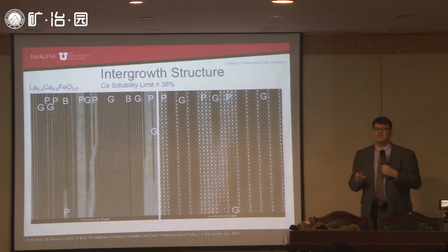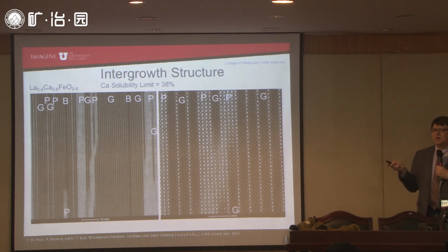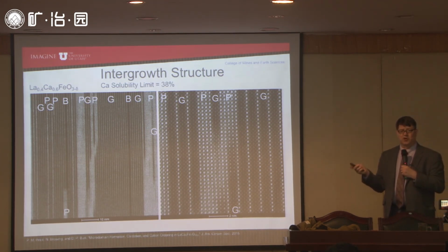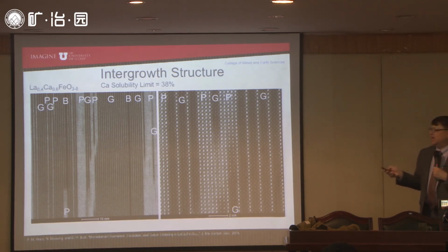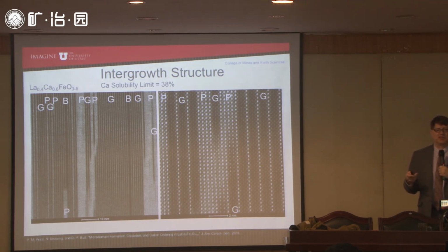And the brownmillerite phase is there accidentally because this is a binary system, and so to have 3 phases in equilibrium at this composition would be a violation of Gibbs phase rule. And so we have this brownmillerite phase here because we don't have perfect mixing.